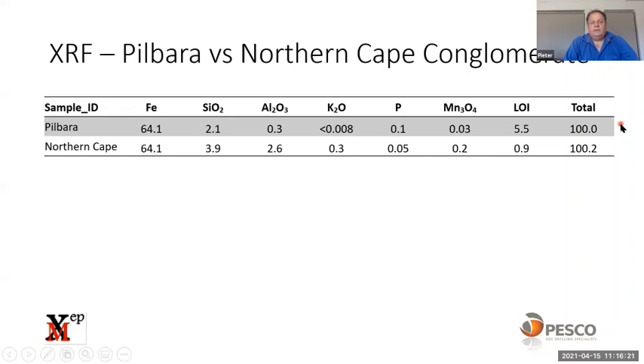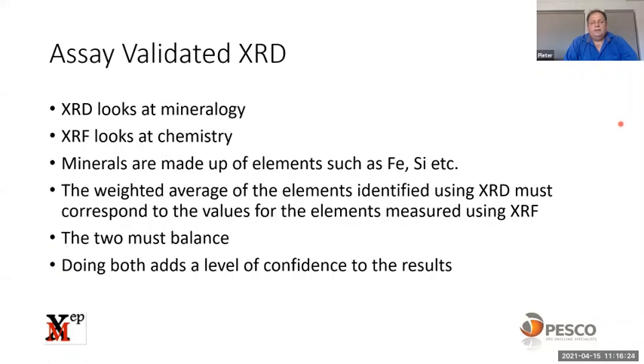If you look then at manganese. Okay, sorry, before I jump to the manganese sample. It's important when you do XRF and XRD that you do it in combination. The XRD looks at the mineralogy, tells you what type of mineral it is, what mineral phase it is. The next slide is your XRF that looks at the chemistry, percentage Fe, percentage silica, etc. And then you use a weighted average to compare that with the XRD. So when you complete your XRD analysis, you use your XRF analysis to make sure there's a balance. That gives you much more confidence in your results. It will tell you exactly the correction factors you need to apply on your XRDs if necessary.